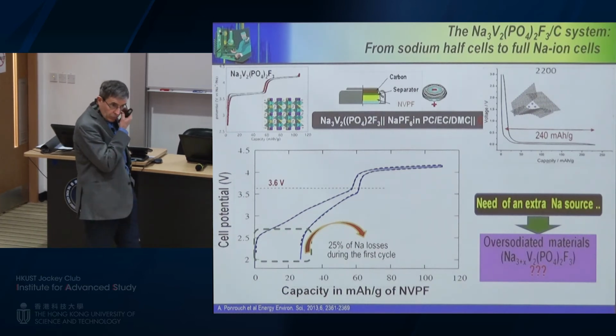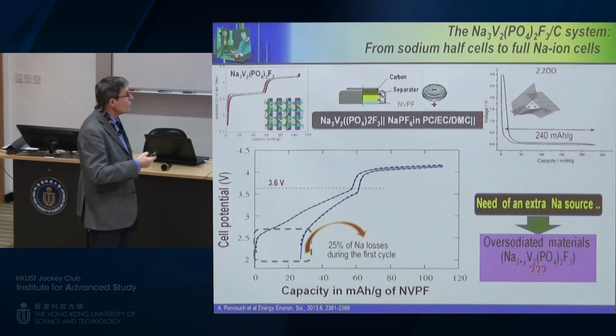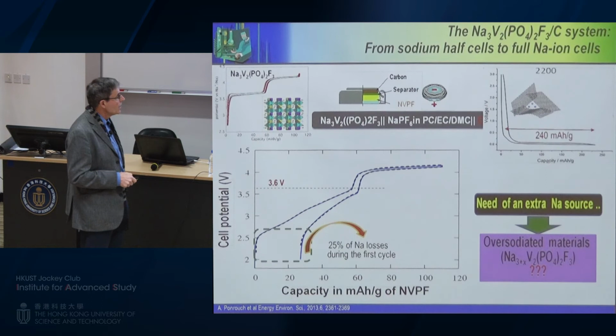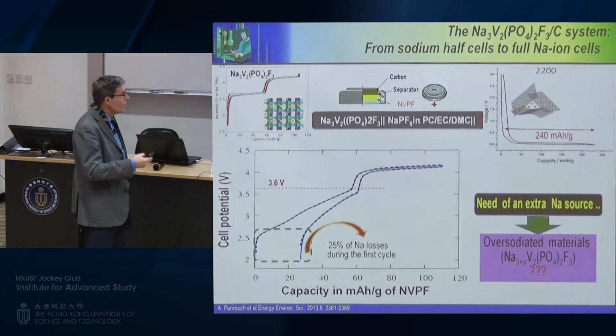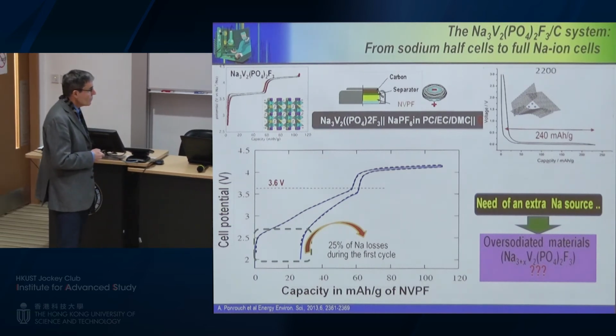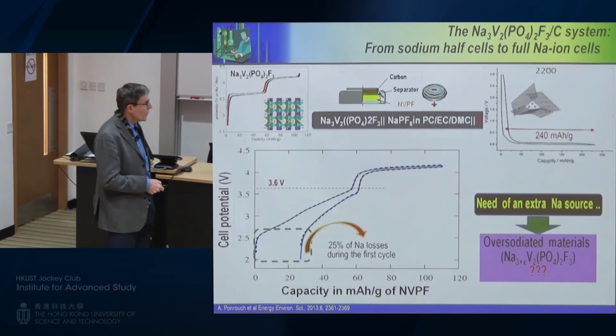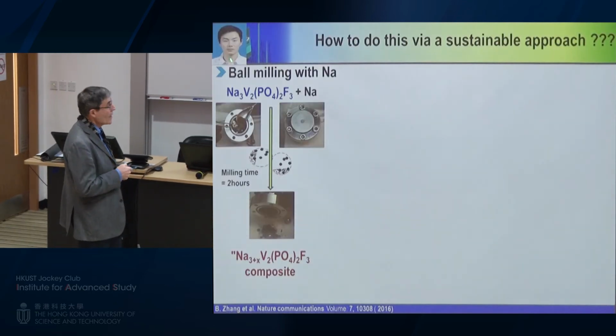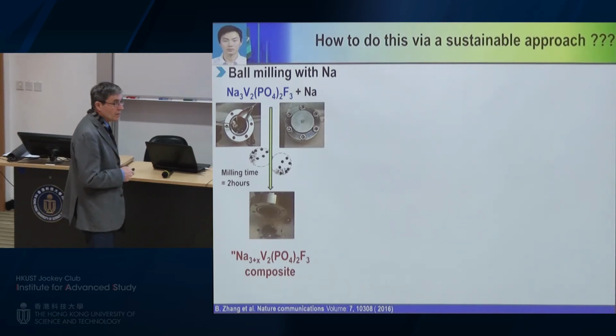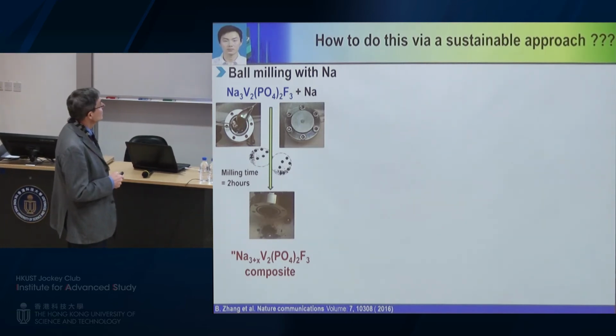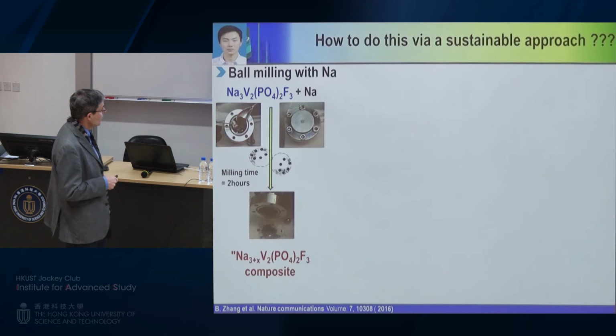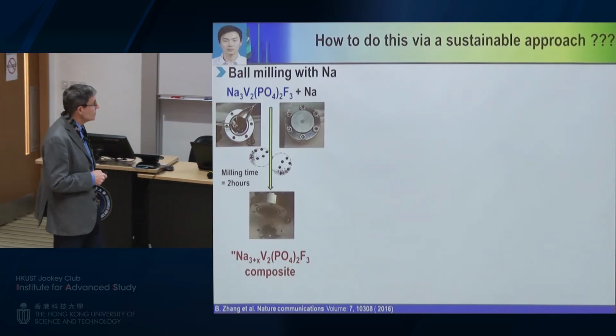And the solution that we propose, which is based on what we have done in the past with lithium-ion systems, is to use extra sodium. Extra sodium, which means in this case we want to build this compound, Na3+x, because you can bring in sodium without adding too much heavy weight to the materials. To do this, we prepared this phase, and it was done by Biao, as a matter of fact, who is here, by ball milling, mixing the NVPF with sodium metal, as clearly indicated here, and he obtained a very nice powder of Na3+x composition.